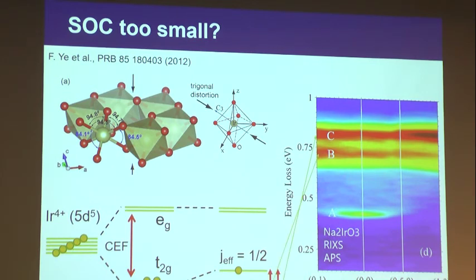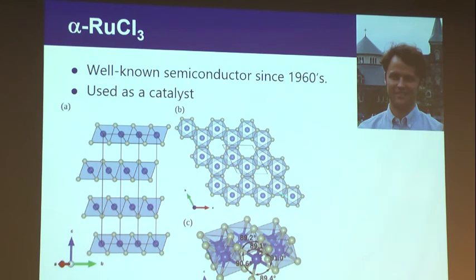And that's when we stumbled upon alpha ruthenium chloride. If you look at the structure, it looks almost like the iridate material that I showed you, a honeycomb lattice structure. But if you look at the individual octahedra, all the angles are very, very close to 90 degrees compared to the iridate I told you about. So the non-octahedral crystal field splitting will be very, very small. And therefore, we have a chance to make the spin-orbit coupling relevant, even in the case of a ruthenium-based material. And this material was actually not new. It's been known for a while.